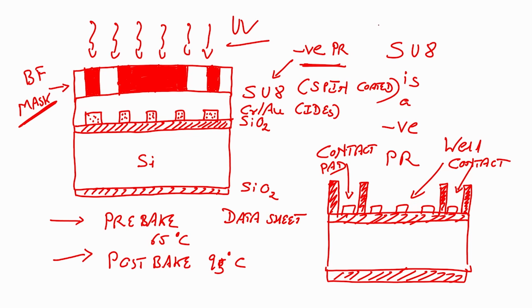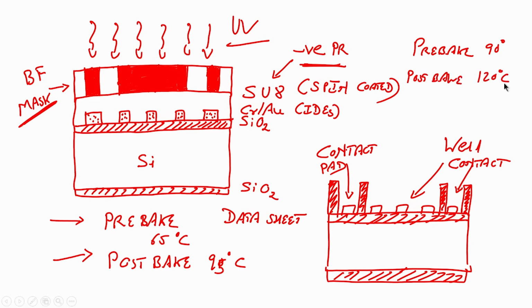If you understand, in the positive photoresist we were pre baking at 90 degrees and post baking at 120 degrees, correct, in the case of positive photoresist. In the case of SU8, we had to pre bake at 65 degrees. Here, after pre baking and exposure we were developing, right.